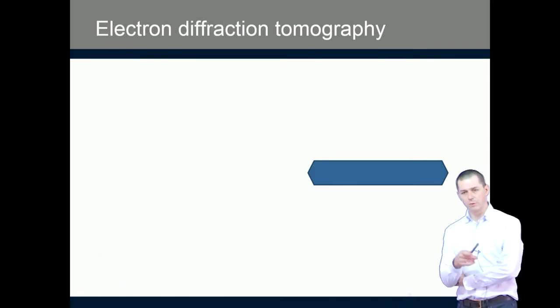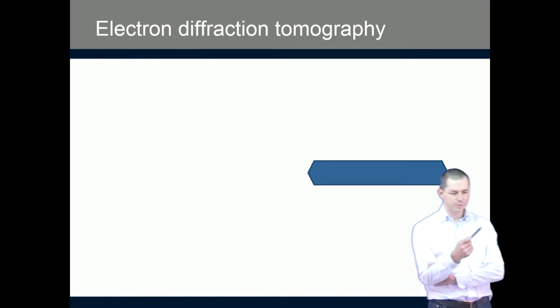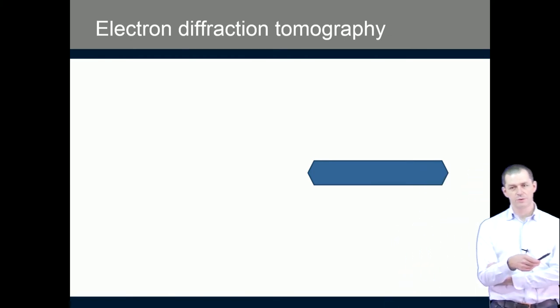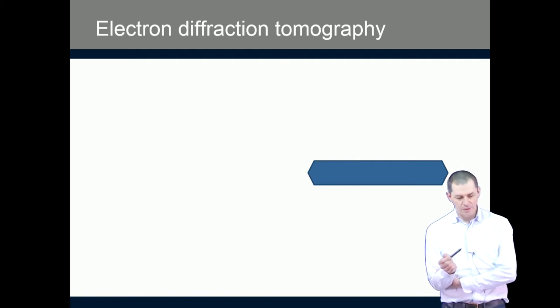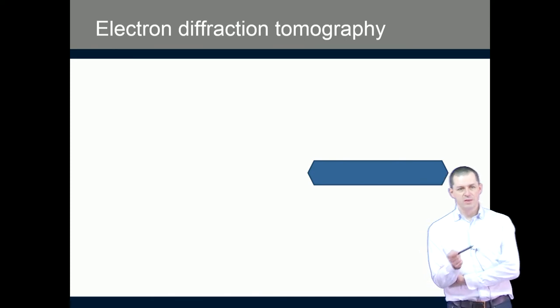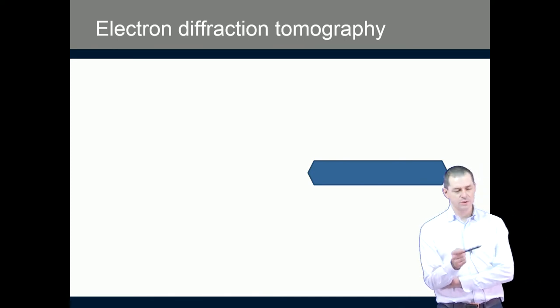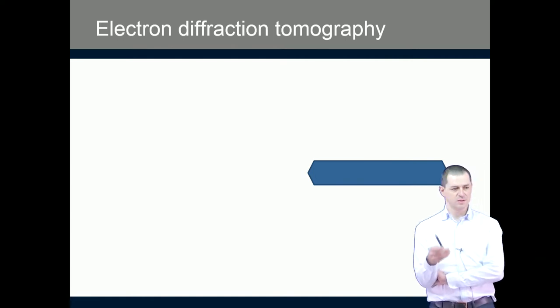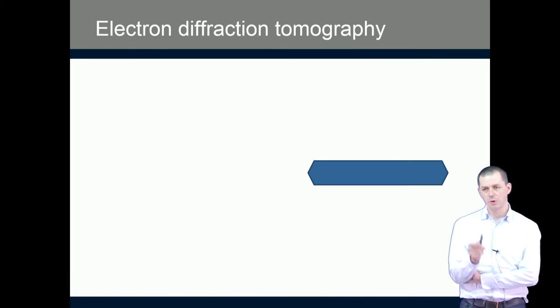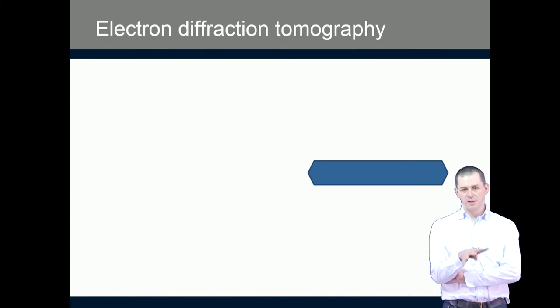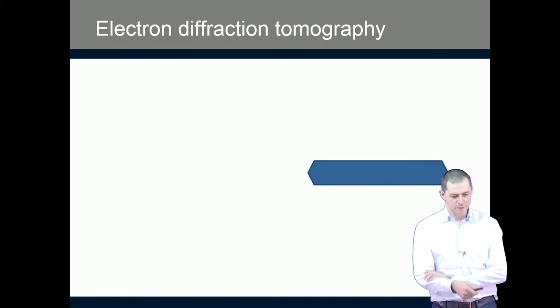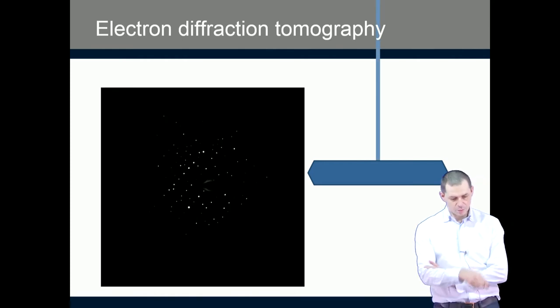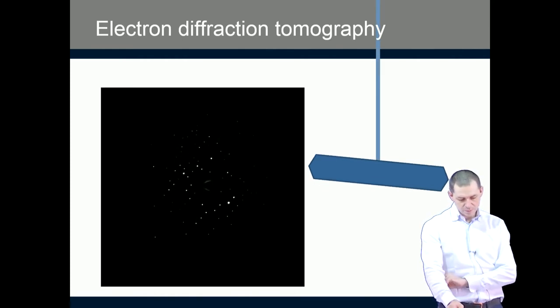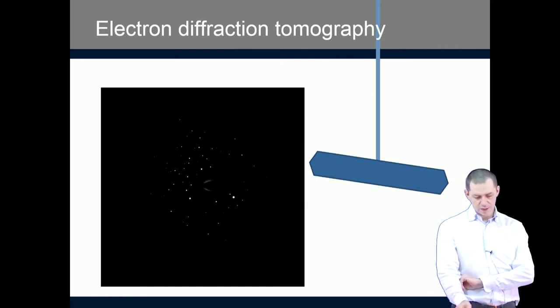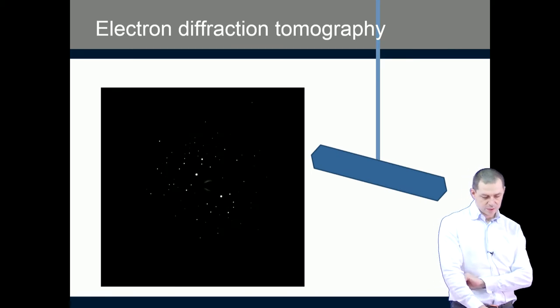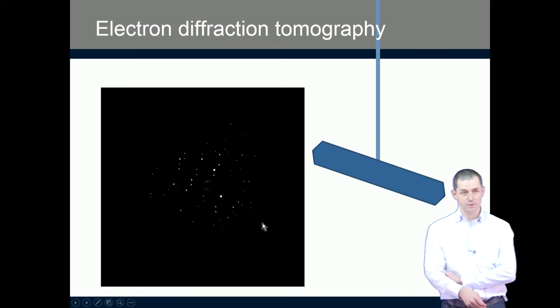In 2007, a group of Ute Kolb, a crystallographer at the University of Mainz in Germany, came with the idea that we could do in the transmission electron microscope the same technique that is usual in X-ray diffraction: recording non-oriented patterns and slowly, sequentially tilting the crystal while recording a sequence of diffraction patterns. So then it looks like this. You have a crystal, you shine a beam through it, and then you tilt the crystal and record the diffraction while tilting, and you obtain a set of non-oriented diffraction patterns from the crystal.